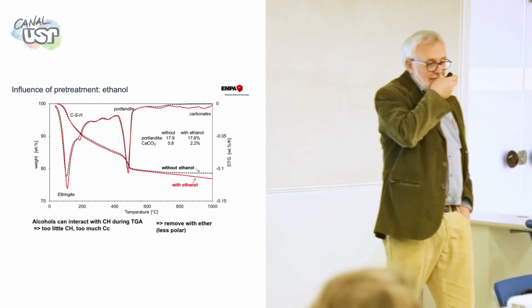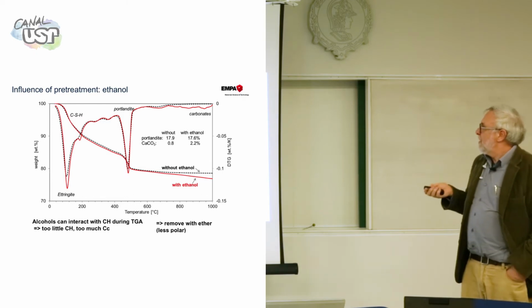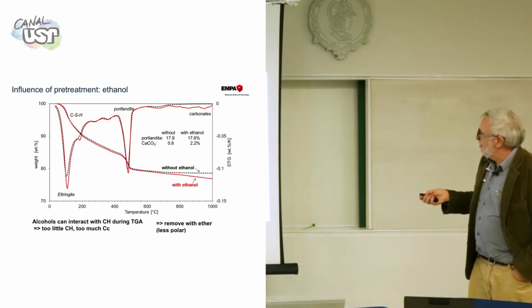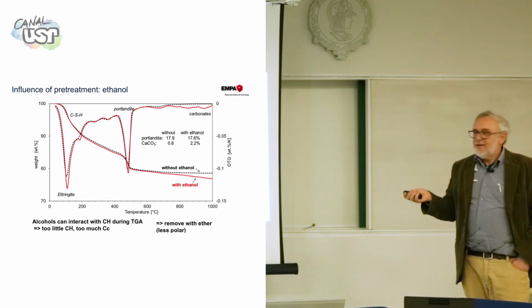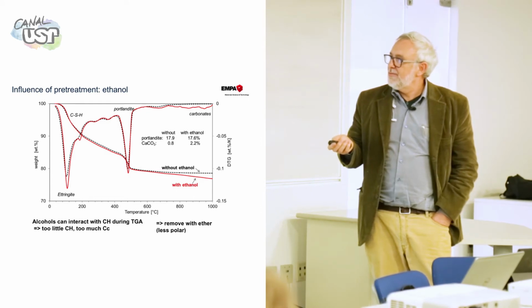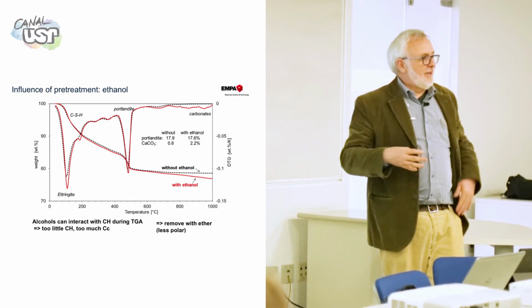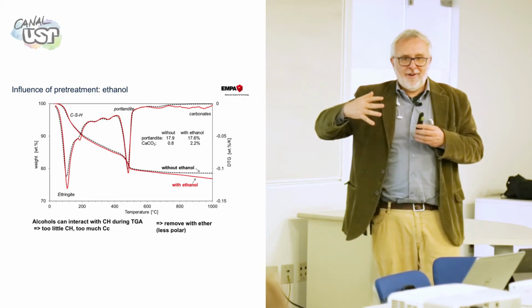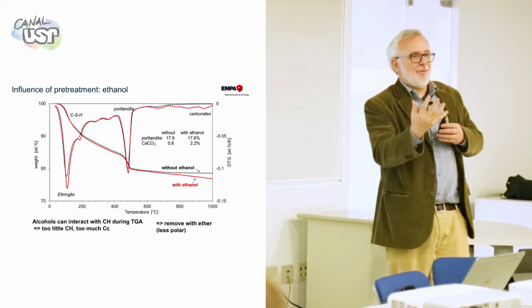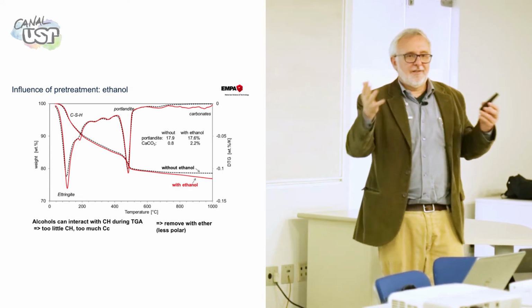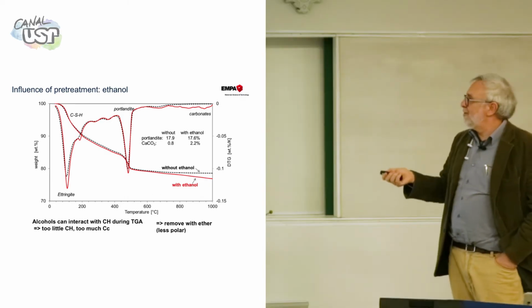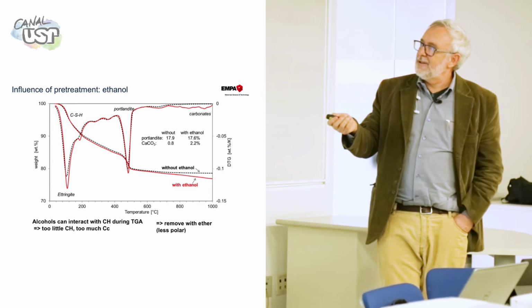It's about the same. Pretreatment, I think Karin already mentioned it. If you stop hydration using ethanol, you are going to have calcium carbonate, because the ethanol will decompose here. This is the ethanol decomposing, and then it generates CO2 inside of the cement. And the CO2, in trying to find a way out of the system, will carbonate the calcium hydroxide that is around. So instead of having Portlandite, you reduce Portlandite a bit and you increase carbonates. Okay? And that sort of thing happens if you have a lot of organics inside.